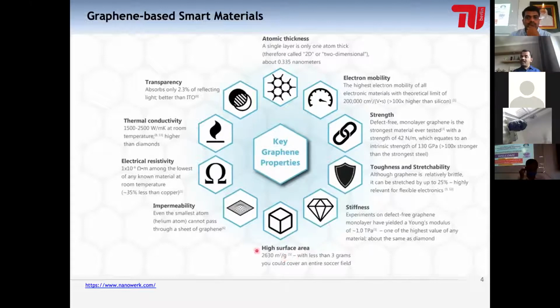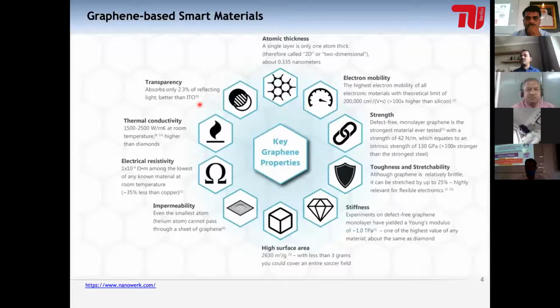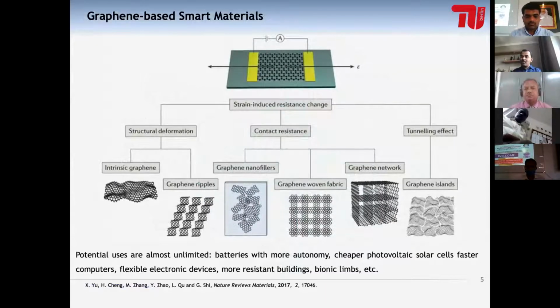And this can be measured by the BET analysis, which we generally do in the lab at 77 Kelvin, 1 atmospheric pressure. They have impermeability. Even the smallest atoms such as helium cannot permeate through, and this could be one of the options to purify water, which gives this material another advantage. They have good electrical resistivity. They have fantastic thermal conductivity, which gives applications of this material into many avenues. And then they have transparency, and that is why we see the utilization of this material in solar cells, and so on and so forth. So due to these properties, these materials have been applied in different ways.